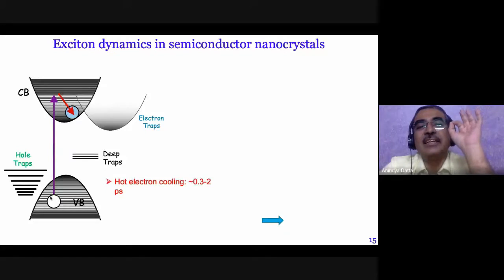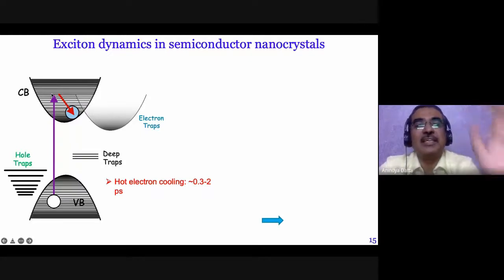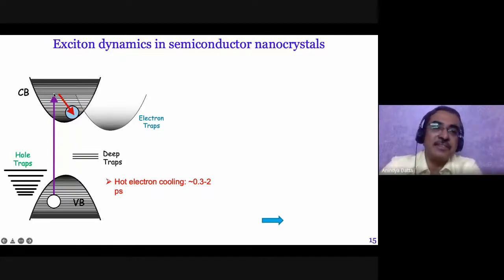There are states that can trap the electron. Even before that, if we perform an above band gap excitation, that means the excitation energy is more than the band gap, then you end up creating what is called a hot electron. Hot electron means an electron that has more energy than what you require to promote it to the band edge. So the hot electron relaxes to what is called the band edge, the lowest energy state in the conduction band, in about 0.3 to 2 picoseconds. It's an ultra fast process.